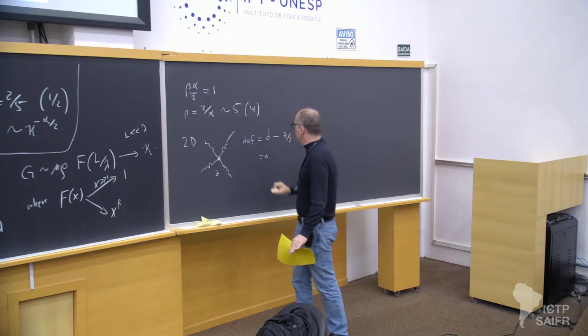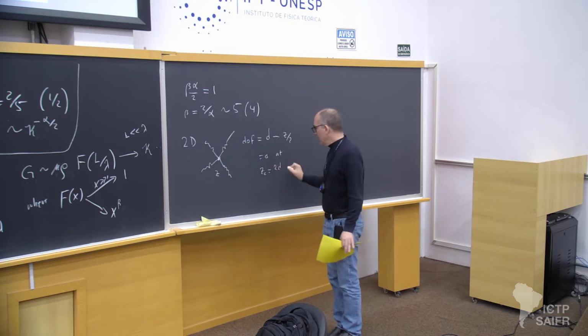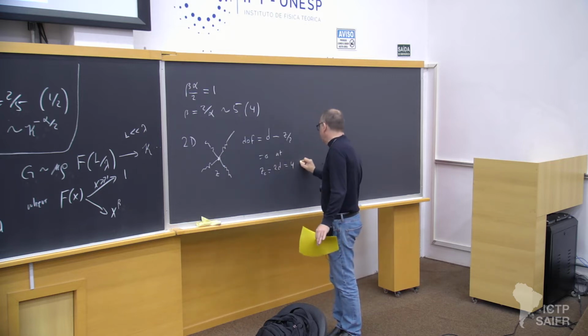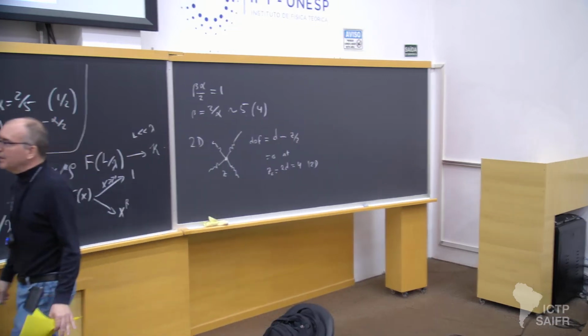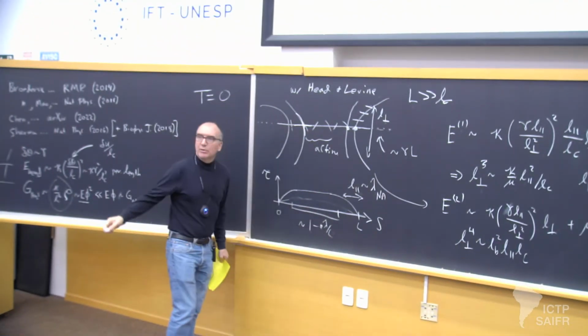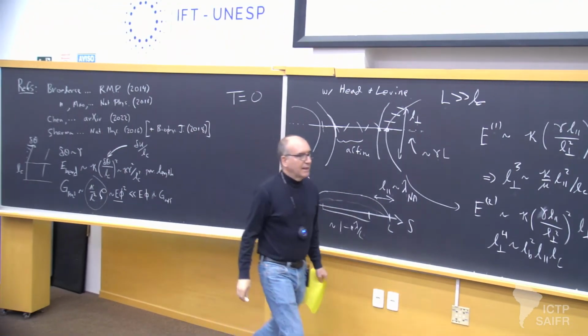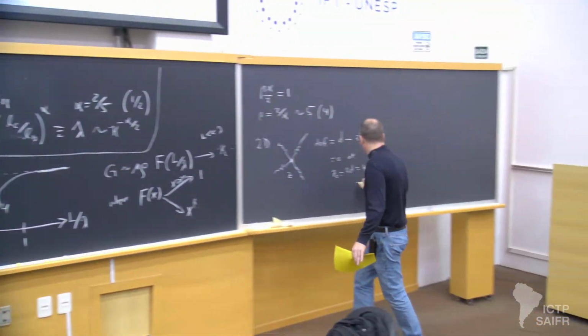And this is 0 at Z_C, a critical or isostatic coordination number of twice D. Now, in 2 dimensions, that's 4. And 4 is exactly the kind of local structure I expect in a network. I've got a crossing point of 2 fibers. In 3 dimensions, that coordination number would be 6.